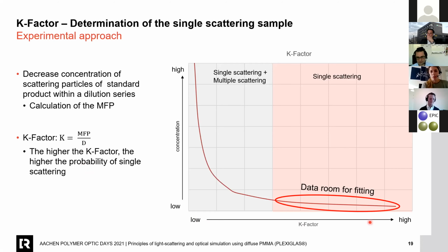On the right, you see a diagram of our dilution series. We start with the real product in the top left. You have a high concentration, so you have a low mean free path and a low K factor, and you decrease the concentration of your scattering particles again and again. Then you go from the multiple scattering range into the single scattering range, where the probability of single scattering gets higher. If you have a very low concentration, you have a high K factor, and that's what you need to measure the single scattering.